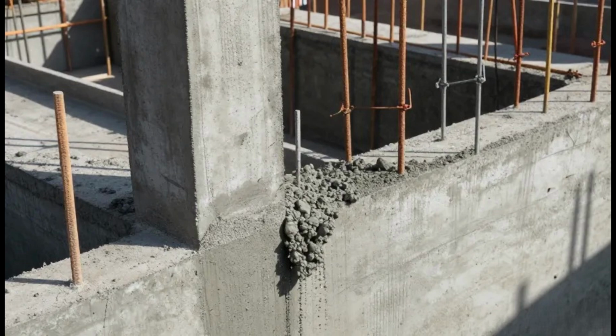He had once failed to ensure adequate cover on a reinforcing bar near a form face, and the bar showed as a shadow in the finished concrete surface, which required remediation. He had once misjudged the set time of a finishing concrete on a very warm day, and the surface was not as well finished as it should have been. He remembered these mistakes. They had not happened again.